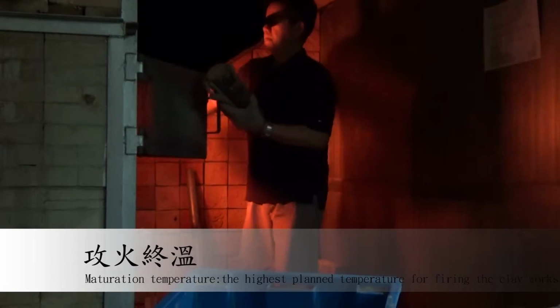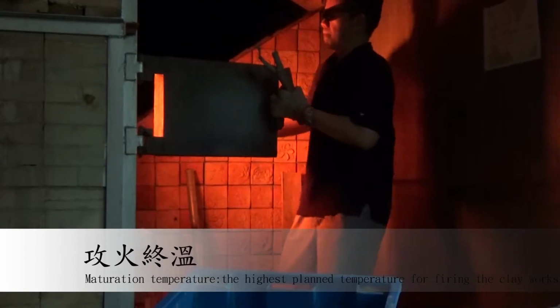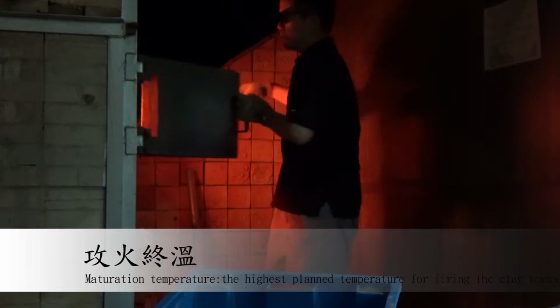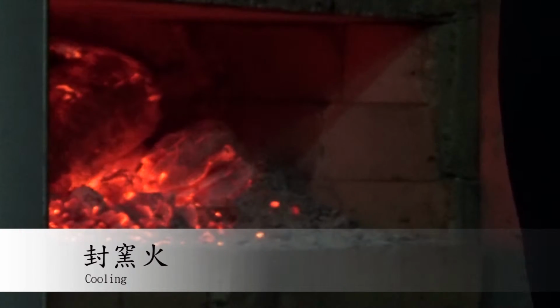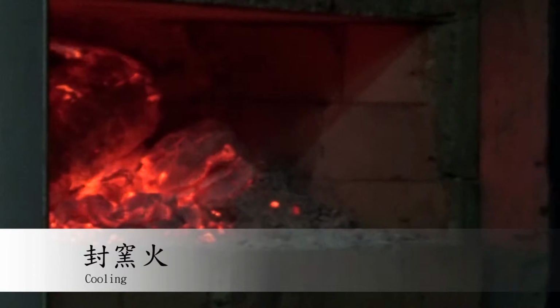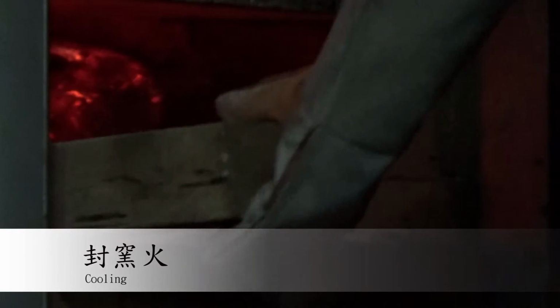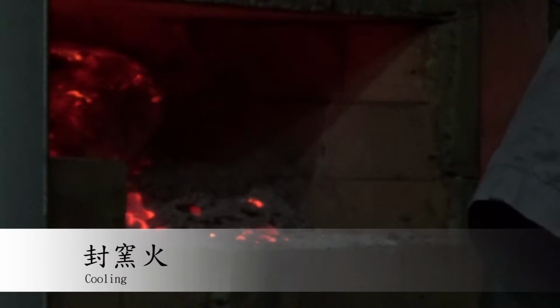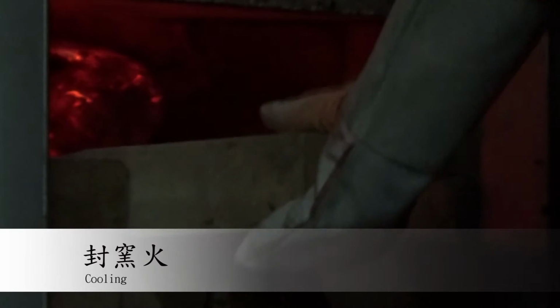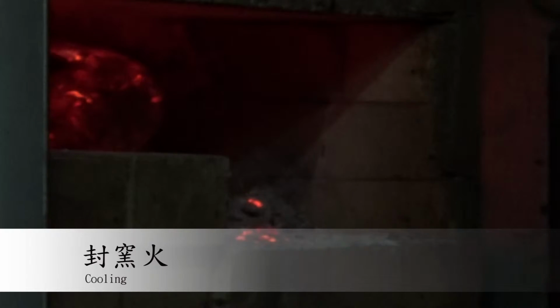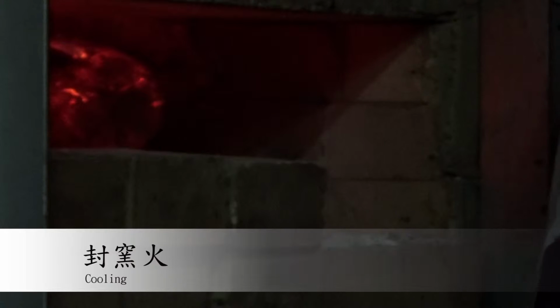Ceramic change. Ceramic change takes place between 350 to 700 degrees Celsius, a process which permanently changes the plastic clay into something rock hard that can never again be softened by water. This process will change a clay work into a pot because chemically bound water is released from the crystal structure and changed the crystals so that they cannot reverse to their initial shape. The ceramic change peaks at around 600 degrees Celsius and can be indirectly observed from the white steam at the chimney.